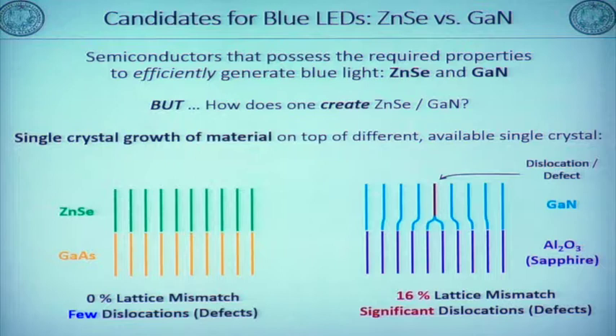No lattice mismatch means the atomic arrangement is almost the same among the 2 materials. So it means no crystal defect when growing zinc selenide on gallium arsenide. But in the case of gallium nitride, the only available substrate is sapphire. So in this case, lattice mismatch is 16%. So it's a huge difference of the atomic arrangement between gallium nitride and sapphire.